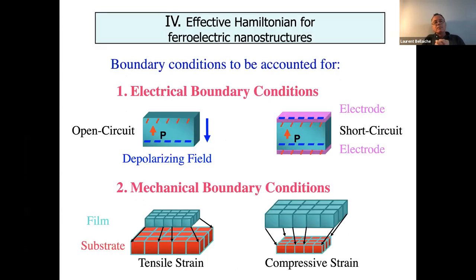So now let me go to something else. It's a development that we did for, I don't know, probably now 17 years. It's effective Hamiltonian for ferroelectric nanostructures. There are two big changes with respect to bulks, and these are about boundary conditions. The first one is about electrical boundary conditions. For instance, imagine you have a polarization that points up. Automatically, because of P dot n, surface charges, the bottom surface will be charged minus, the top surface will be charged plus. From plus to minus, you have a field that is created. This is the depolarizing field, and this guy is against the polarization.